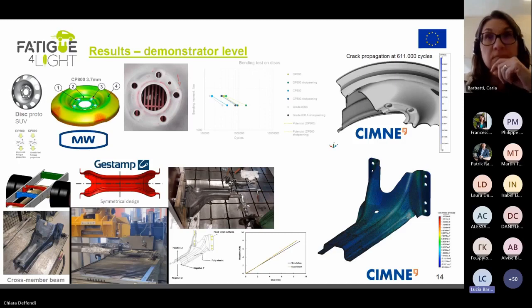So they manufactured half a beam. And you can see the test setup where the beam was screwed to a plate. And then the cyclic loading, first the monotonic loading, but afterwards cyclic loading, was applied to the end of the beam in several directions to study the performance of this demonstrator, which was manufactured with the press hardened steel 22MnB5. From CIMNE's side, we also wanted to study the performance numerically. And at the moment, at least for the monotonic case, we are obtaining quite a good approximation to what was seen in the test. Okay, now let me go forward.